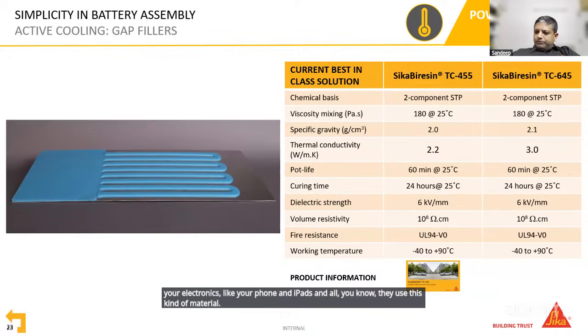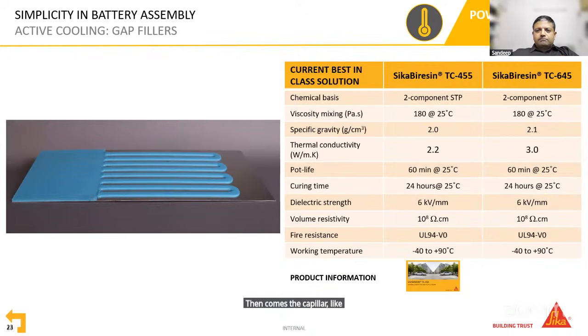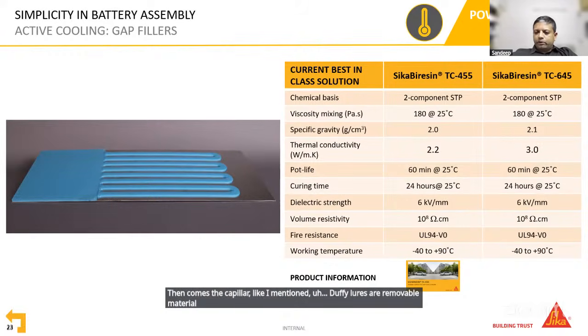Then comes the gap filler. Like I mentioned, gap fillers are removable material, and this has got very low mechanical strength, probably about 0.1, 0.2 MPa compared to 11 and 15 and above for the thermally conductive adhesive material. But thermal conductivity for thermal gap fillers is pretty high. It starts from 2.2 and goes up to 3.0 watt per meter Kelvin.